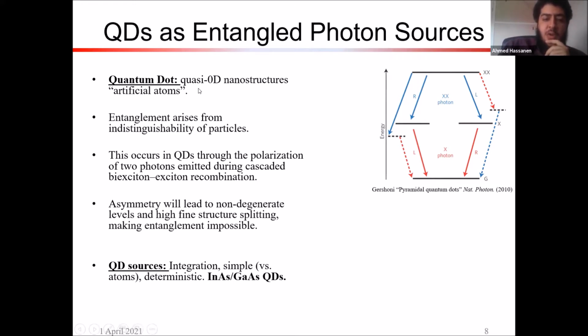And so basically, a quantum dot is this quasi zero-dimensional nanostructure. It's been referred to sometimes as an artificial atom. So you can get these distinct energy levels, rather than just like in bulk. And so for entanglement, the key thing to realize here is that you need to have really indistinguishable particles. So there can't be any degree of freedom between them that's different. And so in quantum dots, how this occurs, if you look at this energy band diagram, is this bi-exciton-exciton cascade or recombination. An exciton is just this quasi-particle that's an electron and a hole bound together by Coulomb forces.